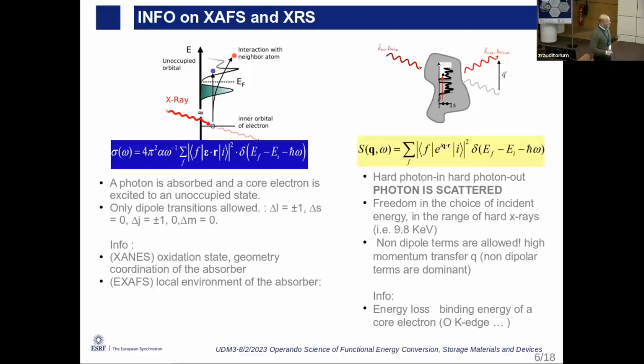This means that we can overcome all the problems of the soft X-ray, which we typically used to measure these low Z elements. And then we can get similar information to what we get from XANES, especially when we go to small Q values. Since this is an inelastic scattering technique, we can measure different angles of different Q. But for low Q, the two techniques are very similar. I would say the information is very similar, so we can distinguish the local environment of the scatterer.